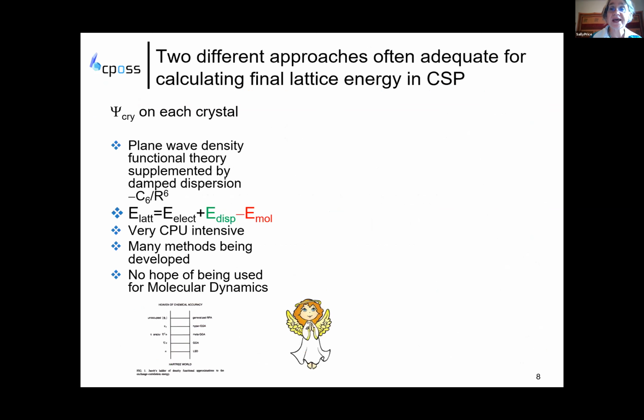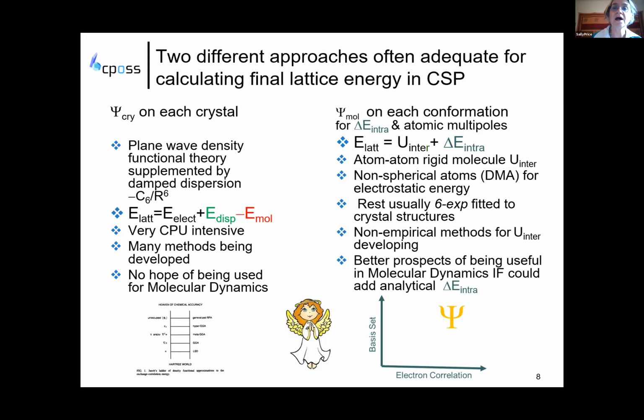So the sort of calculations we're doing, some groups, including the commercial ones, now will do periodic density functional calculations on hundreds or thousands of low energy structures to get their relative energies. These methods have to be supplemented by damped dispersion, and they're only able to use fairly simple functionals such as PBE. And it's very expensive, and there's no hope of extending this to molecular dynamics methods.